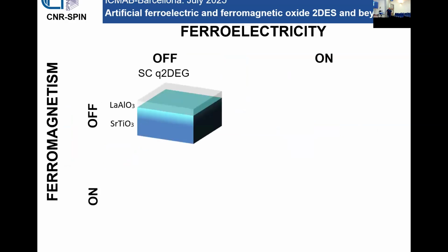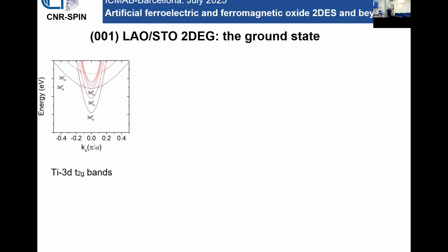So we start essentially from the LaAlO3 system. We combine these two band insulators. Just a few words about the properties of LaAlO3/SrTiO3 2DEG. The physics is the one of bands which originate from titanium 3d t2g orbitals. But due to the confinement, these bands are split. The splitting is about 50 millielectron volt, and so by tuning the Fermi level, one can access single band or multi-band physics, which is also an interesting property.